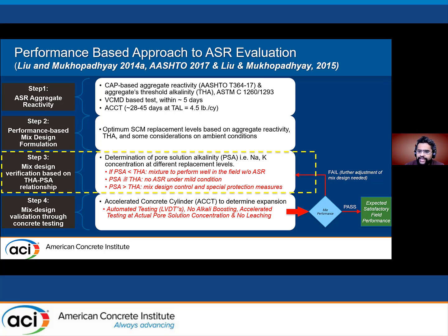Once we determine the aggregate reactivity, the next step would be deciding the optimum SCM replacement, which is a performance-based mix design formulation. Now, for this, we really need to evaluate what the pore solution chemistry is for each concrete mix for different SCM replacement levels. And once we have the pore solution alkalinity determined, we would go to step 3.